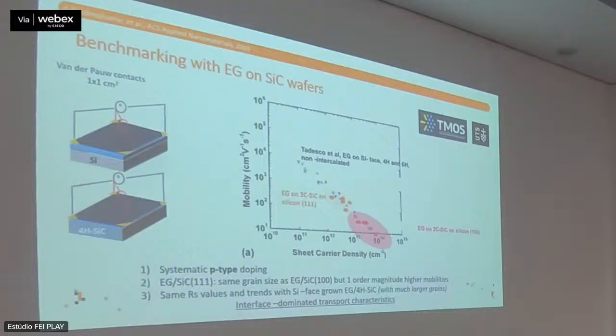And that's very important to know because, of course, when you are on this high sheet carrier density, you will never be able to get very high mobility. On the other hand, if you can reduce the sheet carrier density, you can climb up and achieve quite a good number of mobility. But we are all the same. So these are all equivalent sheet resistances. So basically, this is very important to understand. And actually, this is where we get to the fact that the interface is dominating our transport properties, not really the grain size. The grain size, at least not in this regime.